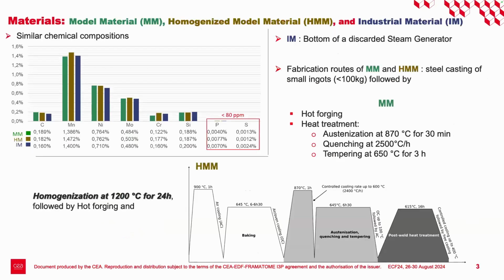So here are the three materials. As you can see on the table at the top, they have more or less exactly the same chemical composition, but we have two model materials, the first one MM and the second one HMM, that have been obtained from small ingots of only 100 kilograms, while the last material, the industrial material, is a part of a very large component that is made from 100 ton or more ingots, so not really the same material.